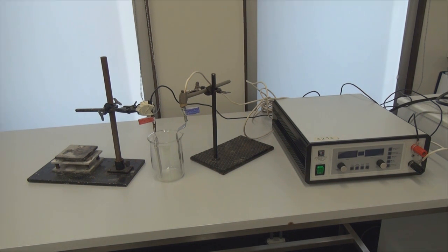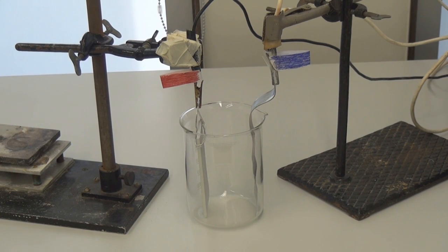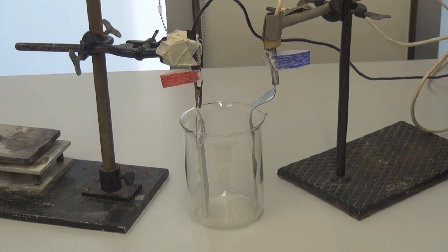Be sure to connect the aluminum object to the positive lead, that is usually red. The negative lead is connected to the cathode, which can be made out of stainless steel. Make sure that these electrodes are separated and parallel to each other.